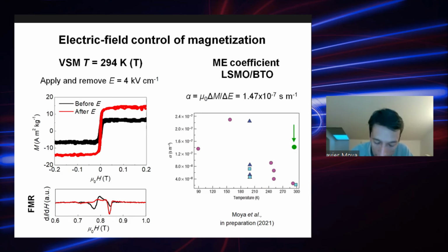So you can quantify this using this magnetoelectric coefficient alpha, which is basically the change in magnetization divided by the change in electric field. And you can see that this graph is comparing this data with the previous data on this material. But this material already was one of the best magnetoelectric systems out there. So you can see that at room temperature, you can increase the magnetoelectric coefficient by a big factor, and then obtain very large magnetoelectric effects in these units.